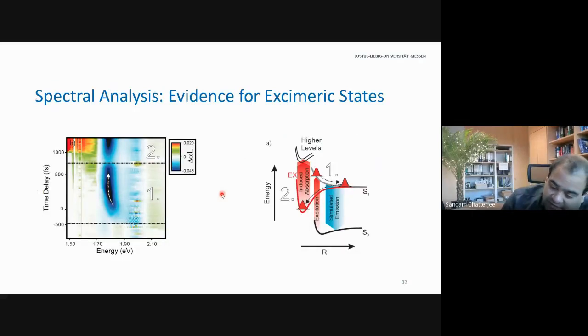We think that we know what's going on in this system, and we think we have excimer formation and singlet exciton fission going on. A part which my grad student was terribly proud of was that he actually could find this little dip here in front after something like 700, 800 femtoseconds, and convinced me that this was not an artifact, so there's a lot of blood, sweat, and tears in this graph. Because what he actually sees, you see a shift of the resonance early on, you see there's an energy change. Then you see something which looked like there's no population, and then you see bleaching of the states. And this he and we explained by the fact that we have a transition into a different parabola, or the excimer regime, which basically depopulates states, but then the states are gone. And this certain transition regime you find on the order of several hundreds of femtoseconds.